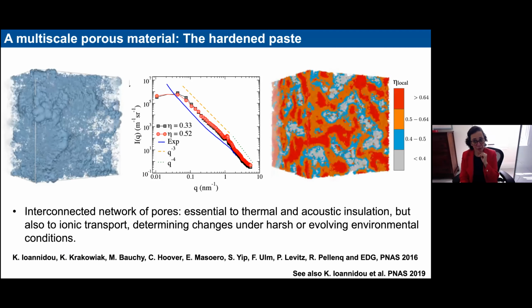And so if we now take these model materials and we let them evolve at very high densities, like what you would get in the hardened paste, which is what you would get basically in your construction, then you can identify the pore structure. This is what you have here. And you can see that there are some large pores in this very dense material, but there is a very fine network of small pores that are actually all connected.